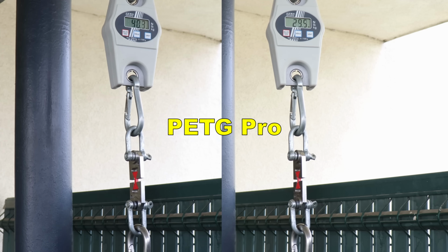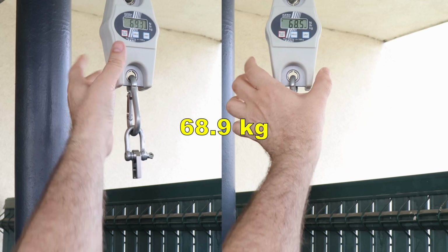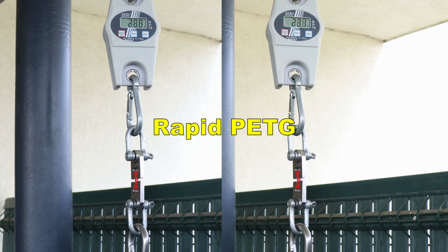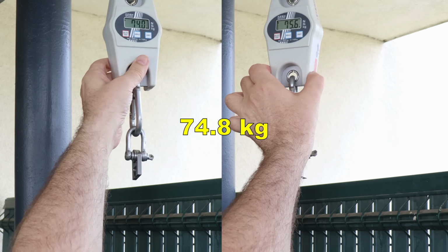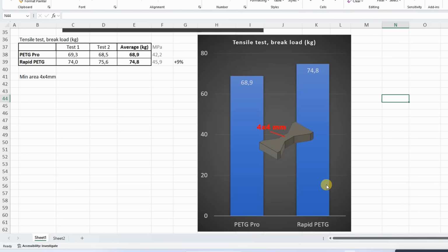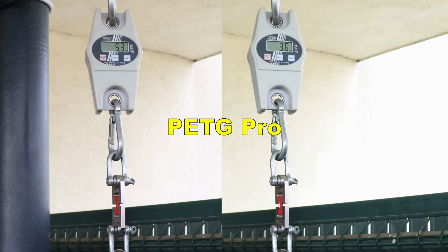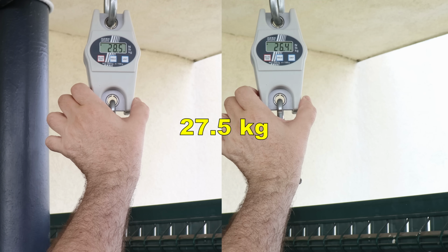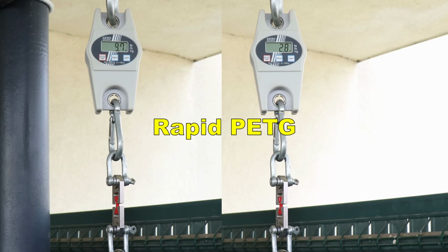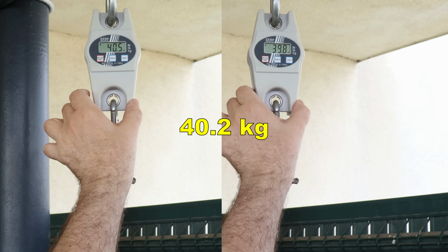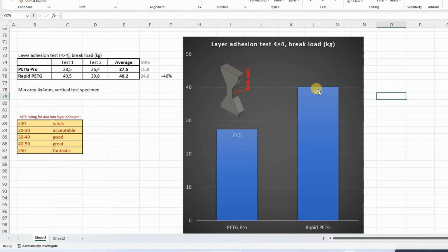Tensile test with horizontal printed objects. This is average from 2. And now rapid PETG. The advantage on the rapid PETG side, the difference is nice but not so significant, only 9%. Layer adhesion test with vertically printed objects. Rapid PETG. These are good values. Now this difference is significant, and I believe that this will be one of the main advantages of the rapid PETG. Flowability is better and layers should bond better to each other.